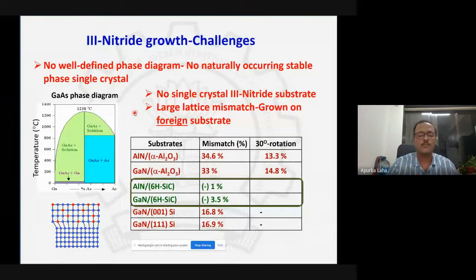1238, for example. So all you have to do in this case is to bring gallium and arsenic in a 50-50 composition, which is a little bit challenging, but if you can make it, then you get a single crystal. In fact, that's the most favorite, the stable phase. So that is not available for III-Nitride systems.